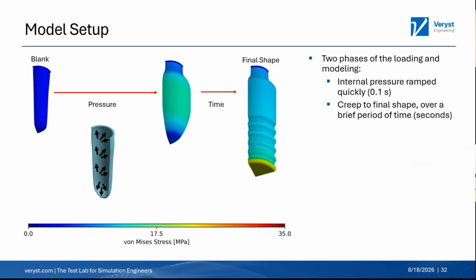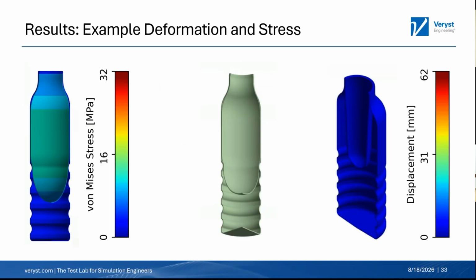So here I'm showing the simulation that we're running. So we're doing a blow molding process. So that one we start with a blank. And then we apply some pressure internally, and this thing blows up, gets larger, and then typically you ramp that pressure up, and then you wait a little bit of time, and the material creeps into its final form, and this kind of looks like a bottle that you might expect there. So we're going to ramp that up quickly over a tenth of a second, where we're ramping that pressure up, and then we creep to that final shape over a brief period of time on the order of seconds to get that final shape that we need.